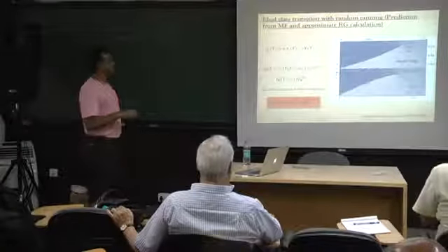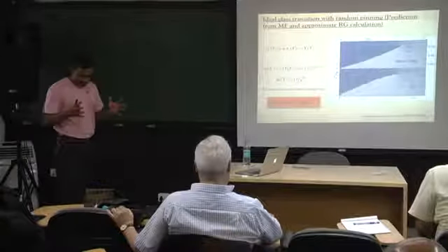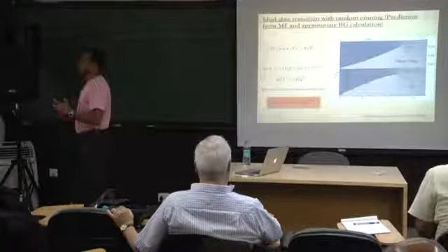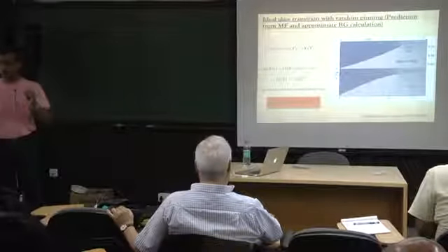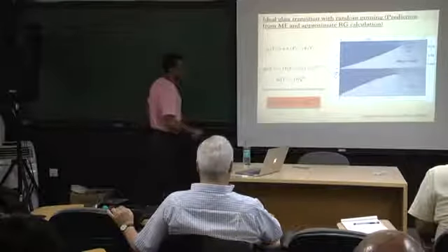This is something called configurational entropy, which is related, in some sense, to the amount of accessible phase space you have. The log of that gives you the configurational entropy. So the configurational entropy, S_C, is given by calculating the bulk entropy and then subtracting the corresponding crystal entropy. Let me put it in a simpler way, though this is somewhat more tricky.